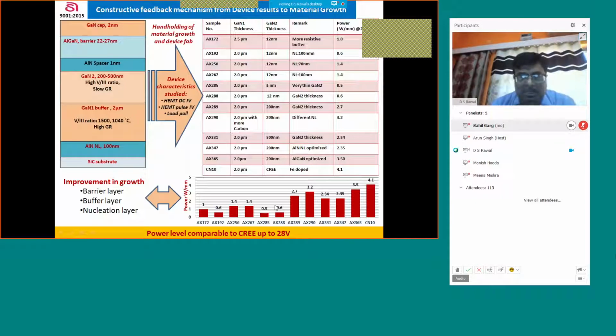But once we started having discussions with our material growth team, there was a continuous interaction between fabrication and growth team, and based on the fabrication results, we improved upon each individual layer, be it a barrier layer or a buffer layer or a nucleation layer. And today we can say that we are almost matching the commercial wafer power output of the order of 4 to 5 watt per mm. And this is mainly because of the hand holding between growth people and device people.